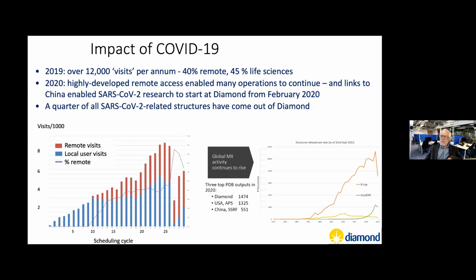That also meant that we were in a good position to collaborate and do work on structures of the SARS-CoV-2 proteins, as Laurent has alluded to. If you just look at the crystallographic structures, probably about a third of them have come from Diamond. It's interesting that a significant amount of the structural work on SARS-CoV-2 has been by electron microscopy. And of course, the majority of that comes from distributed labs around the world. But again, a fraction of that comes from the eBIC Center at Diamond. And it was because of good international links, especially with China, that we were able to kickstart the work in Diamond and with external collaborators on the SARS-CoV-2 structures.